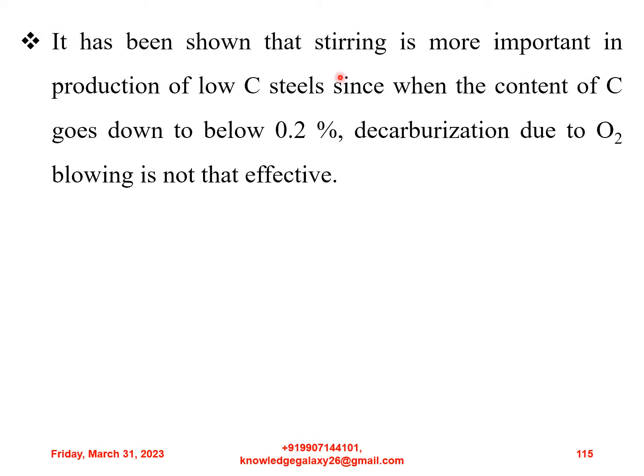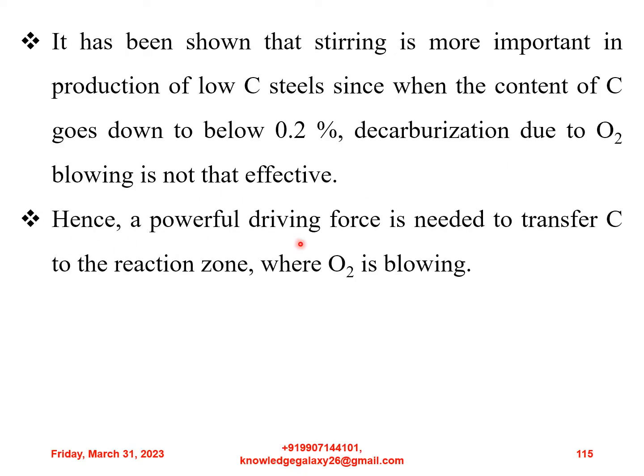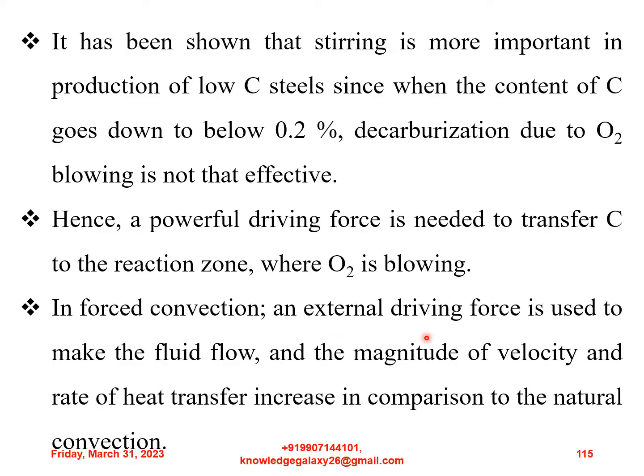It has been shown that stirring is more important in production of low carbon steels, since when the content of carbon goes down to below 0.2%, decarburization due to oxygen blowing is not that effective. Hence, a powerful driving force is needed to transfer carbon to the reaction zone where oxygen is blowing. In forced convection, an external driving force is used to make the fluid flow, and the magnitude of velocity and rate of heat transfer increase in comparison to the natural convection.